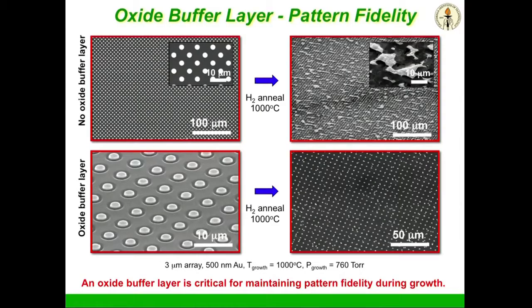So we developed a process by which this works. Again, I'm condensing, in this case, 6 months of work into one slide. We tracked down why people, including us, kept getting that felt-like morphology. Even when we patterned deliberately with photolithography gold dots onto a silicon substrate, we found the reason we grew felt was we don't maintain the integrity of that pattern under growth conditions. Even in the absence of chlorosilane, just under reducing conditions, of course, SEM shows that after 10 minutes, under growth conditions, all those metals don't stay put. They move around and they agglomerate and anneal. And so even if you take pains to start with this template, this is what you get 5 minutes later, and it's no surprise that stuff grows everywhere, all over the place.